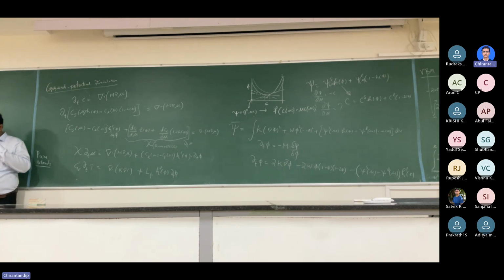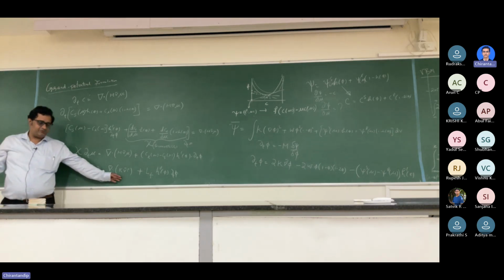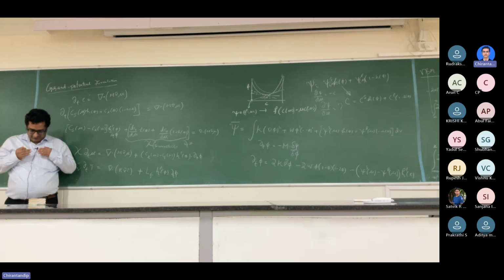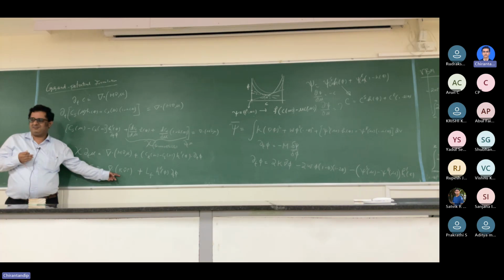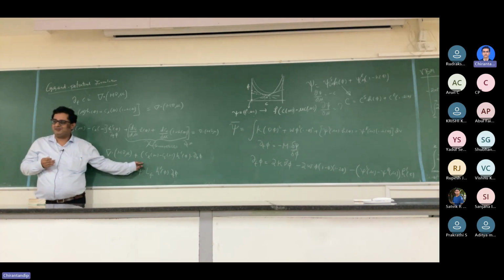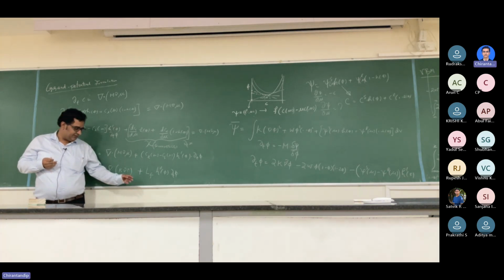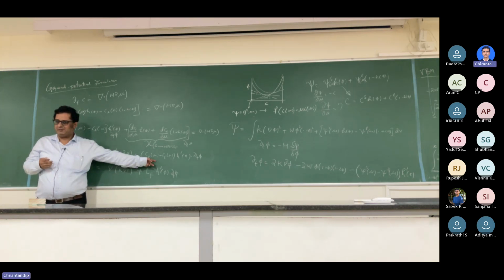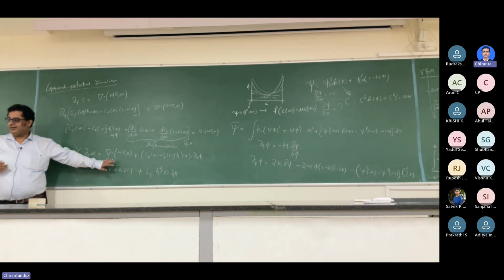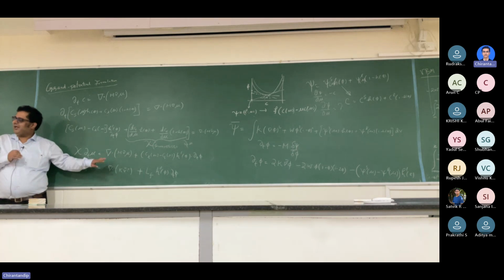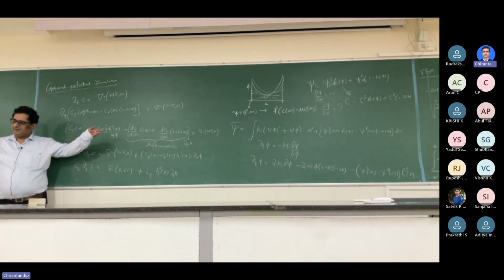When solidification happens in an alloy, what happens in front of the solidification interface? So here, what is rejected? Here, solute is rejected. So this is repartitioning of solute. Here, repartitioning at the interface. Okay, this latent heat is repartitioning. Exact similarity in the equation. Right? Same principle is what we use for the pure material, and in this case, no deviation.